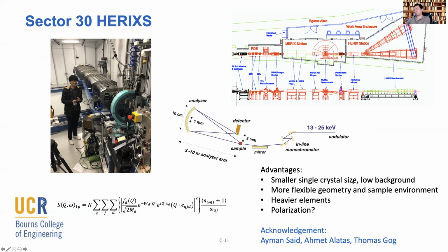We are able to work with smaller single crystal sizes, which is a big limiting factor for neutron scattering, since we usually need a gram or tens of grams of single crystal for reasonable neutron scattering work. On the other hand, we can work with much smaller crystals with X-ray. Also, X-ray has lower background and is considered a cleaner method. We also have more flexibility in terms of scattering geometry, since we usually can put the sample on a 4-circle stage, which allows more degrees of freedom than we can usually achieve on a neutron beamline, where we have to be more hands-on if we decide to change the scattering geometry.